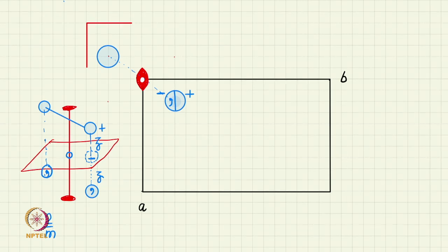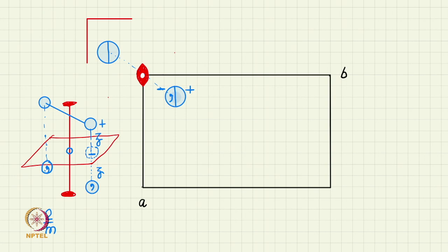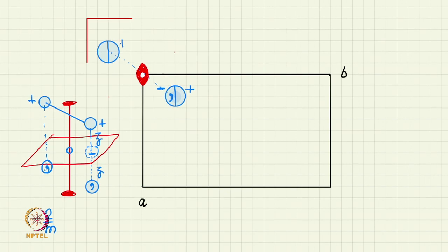So, again in this new location you will have both the handedness objects, and the height does not change due to the two-fold rotation perpendicular to the mirror. So, plus will remain plus, minus will remain minus, and left-handed will remain left-handed, and right-handed will remain right-handed. So, we will get another two equivalent positions there.